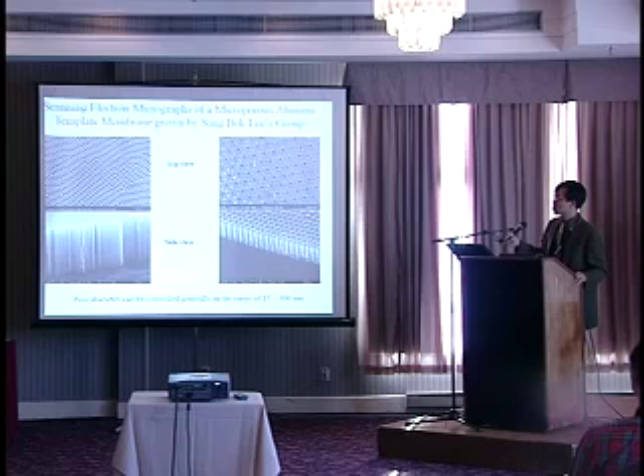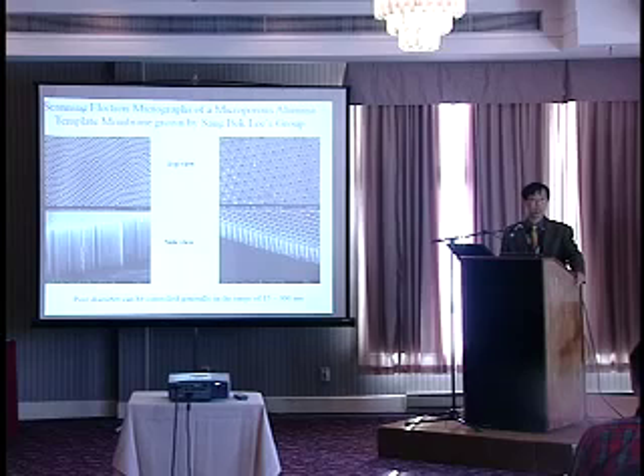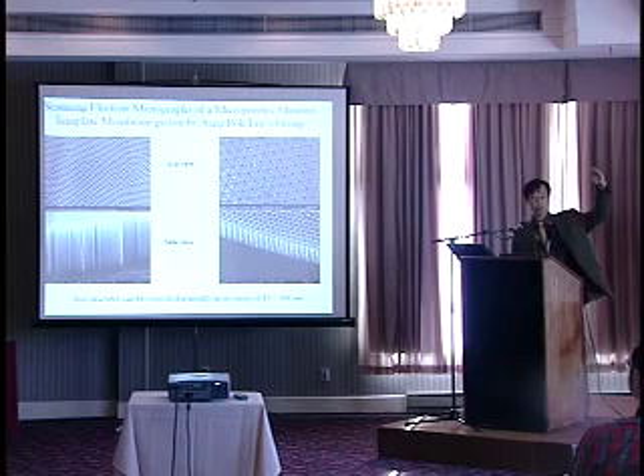When you look at these SEM images, it's almost monodispersed in pore size. And when you look at the cross-section here, each pore has a very nice cylindrical structure. Certainly, the pore structure can be controlled. It's generally from 15 to 300 nanometers, but if you want to go down to 5 nanometers, you certainly can, using different anodization conditions. Also, the length of the pore can be controlled, generally from 100 nanometers to a few hundred micrometers. So the aspect ratio can range from extremely short to extremely high.